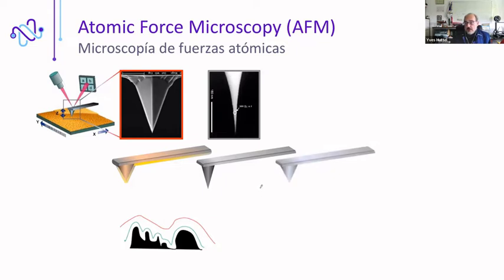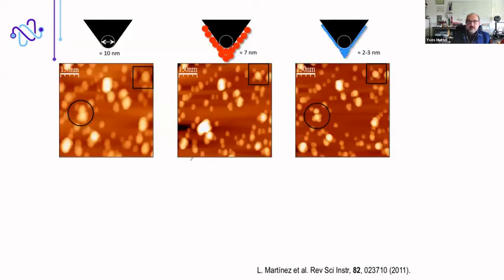And what we came up with is, instead of depositing a continuous capping layer, to deposit a nanoparticle coating in such a way that the very last nanoparticle at the end of the tip will act as the probe in your microscopy measurement. And we tested this by measuring nanoparticles. As you see, we have nanoparticles everywhere because we make nanoparticles every day. But this is a substrate of silicon covered by nanoparticles. And we measured this surface with a tip with an apex of 10 nanometer diameter, the same tip covered by nanoparticles of 7 nanometer diameter, and a tip covered by very small nanoparticles of 2-3 nanometer.